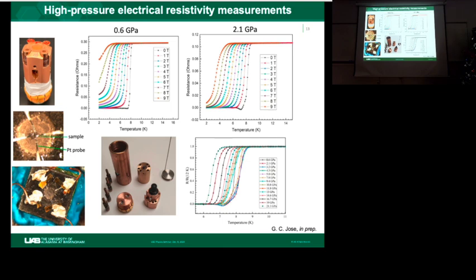So what we've been doing is we have these probes laid out on top of a gasket. This is actually a rhenium gasket, and we have an insulation layer on top of the metallic gasket, and we have the probes laid out, and we load a piece of sample on there. And we also have ruby. Of course, this was done in the lab, so we don't have access to synchrotron X-ray, and the only way to measure pressure is through the ruby fluorescence.